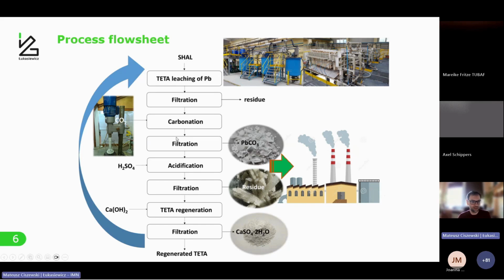In this step, you have quite a big amount of CO2 dissolved in the solution, so the best way to remove it is to acidify it with some sulfuric acid, so you have desorption of the CO2. And the last step, quite challenging but also very positive for the whole technology, is the removal of excessive sulfate ions, which allows us to regenerate the triethylene tetramine water solution, which can be used for another leaching operation.